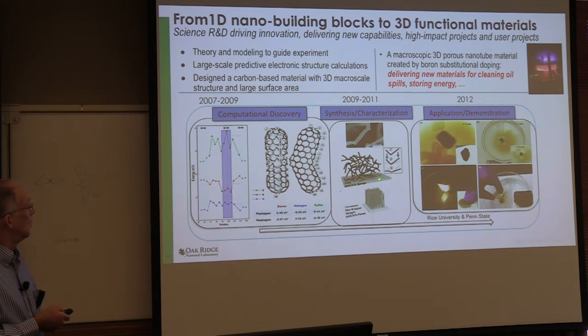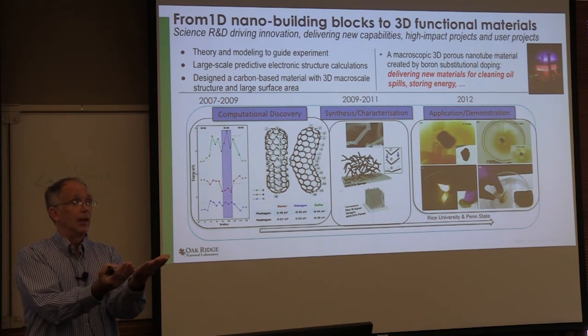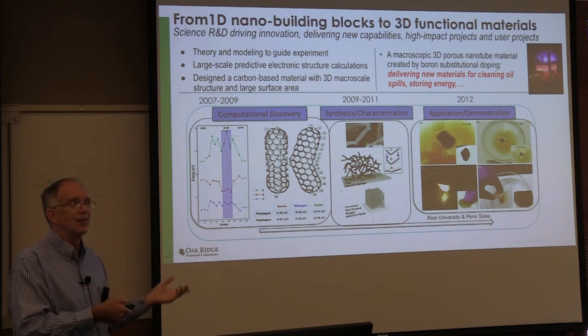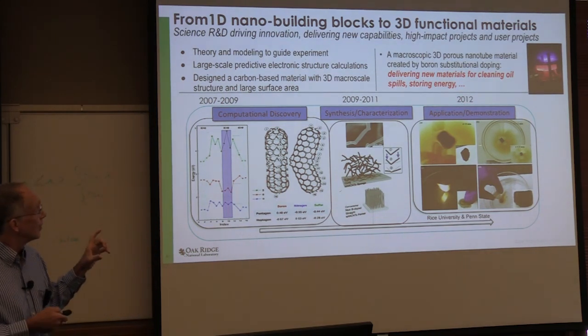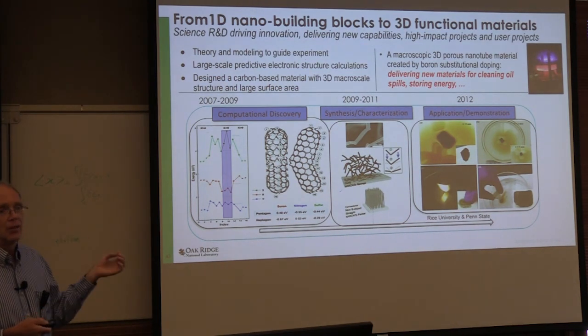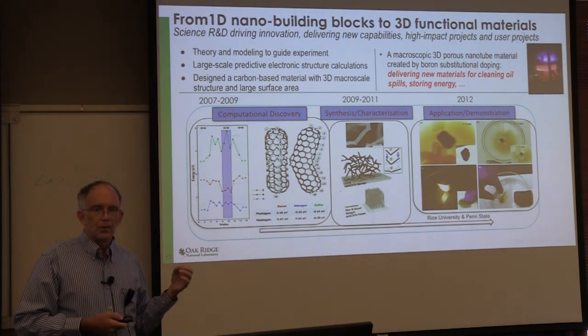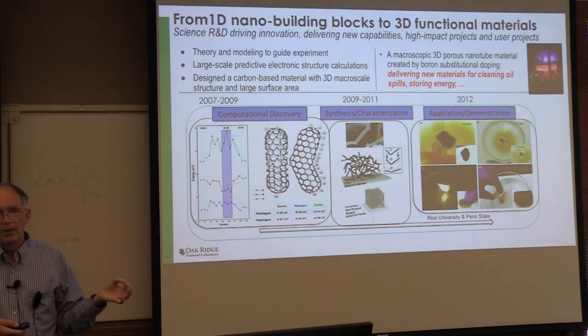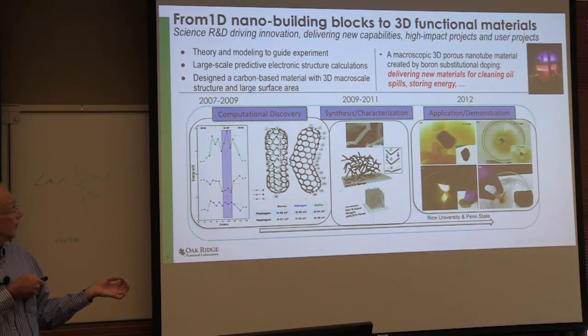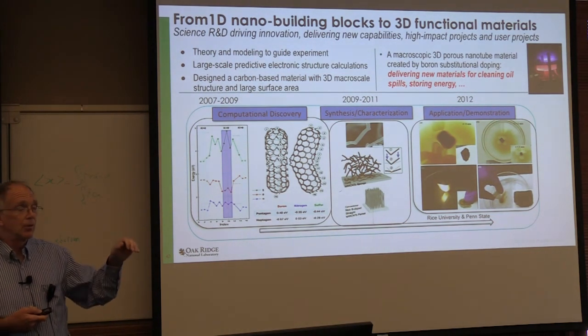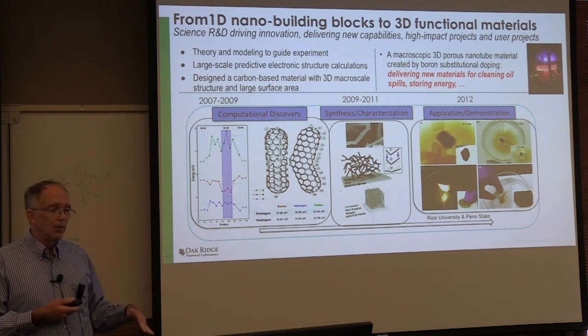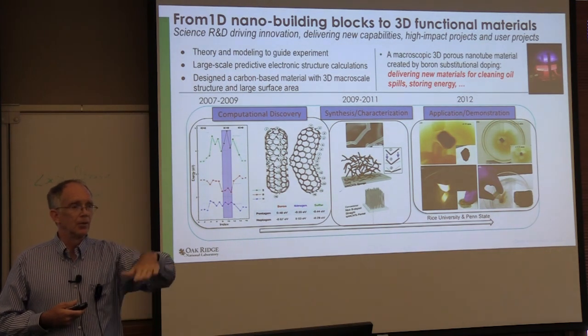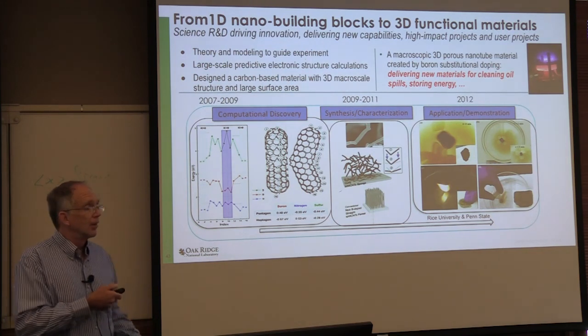You say, so that's cool. How big is it? Well, it's big. You can hold it in your hands, whereas this is very tiny. This is nanometers, right? So this is macroscopic. So this actually does work. The inclusion of another element, boron in this case, nitrogen won't work. Turns out we proved that from the calculations. It'll just close to. The boron actually promotes the formation of negative curvatures, which is just the direction of the growth, and the continued growth.